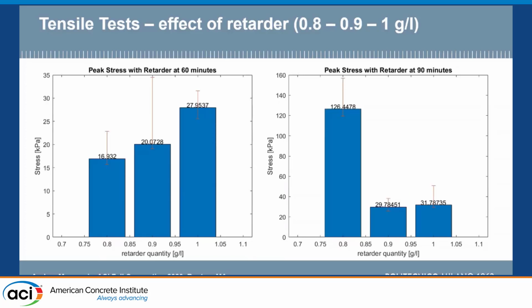And again, no clear trend here, meaning that the peak stress is not increasing with the quantity of the retarder, whereas there is a clear dependency on the least quantity of the retarder, as the peak stress is one order of magnitude different compared to the peak stress at 60 minutes if we look at the peak stress at 90 minutes.